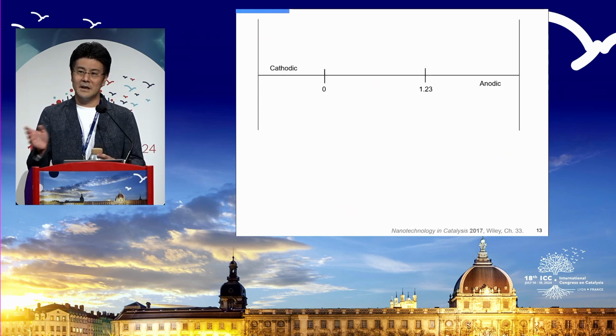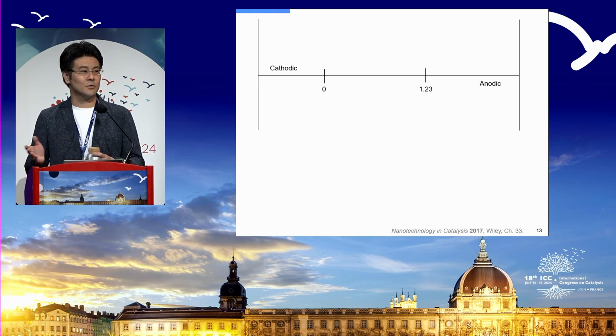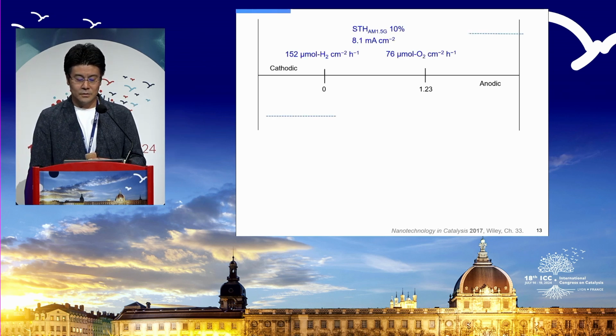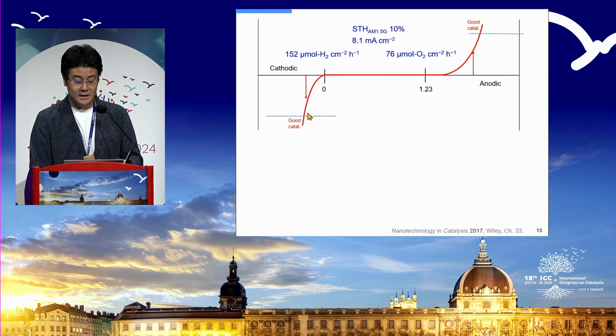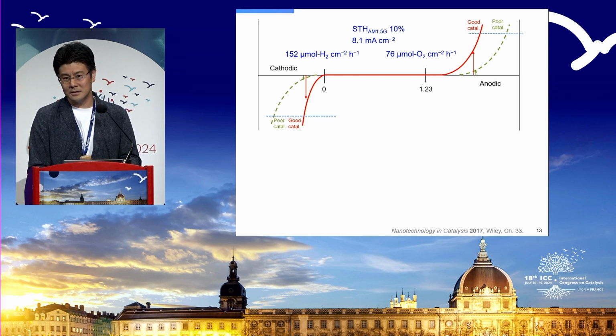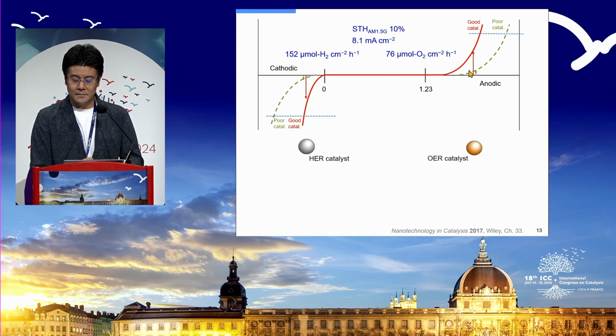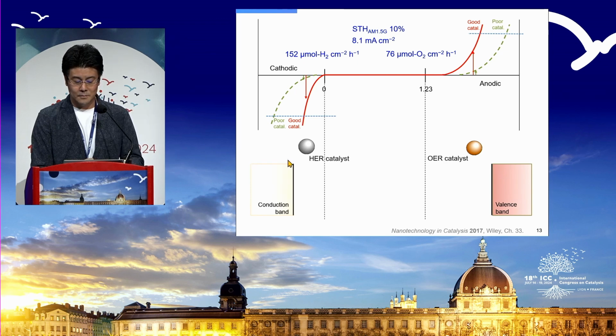So I translate this for electrochemistry people. We use this IV curve, or JE curve as it is often called. What we need to target is 8.1 milliamp per square centimeter in both directions, hydrogen side and oxygen side. We need to have a good electrode material. This slope is sharper if you have a good electrocatalyst; if you have less quantity or a bad electrocatalyst, of course, this slope will be longer, right? In this case, an oxygen evolution like this. So we definitely need a good hydrogen evolution catalyst and oxygen evolution catalyst, and we need to straddle this overpotential with these band edges.